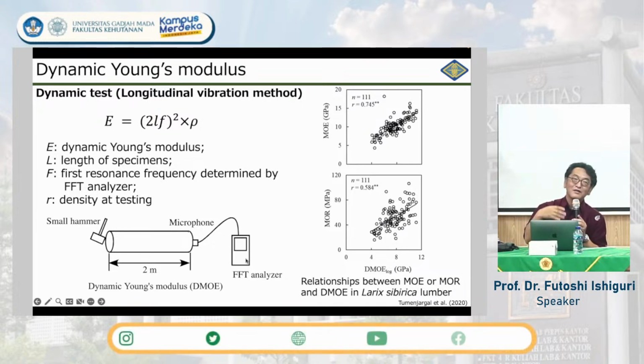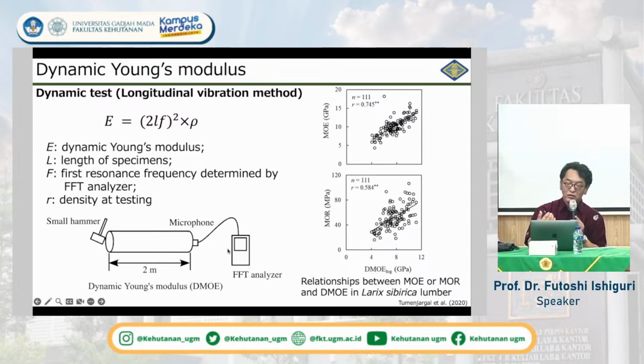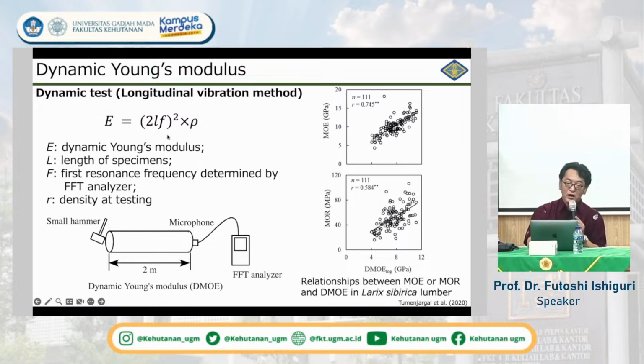So the estimation is good. You can calculate the Young's modulus just by using your smartphone. That is very good. To get the resonance frequency by using the FFT analyzer, and after that we use this formula and get the Young's modulus. And this Young's modulus value is closely related to the destructive test results, like the MOE and MOR. So it is a very good method.